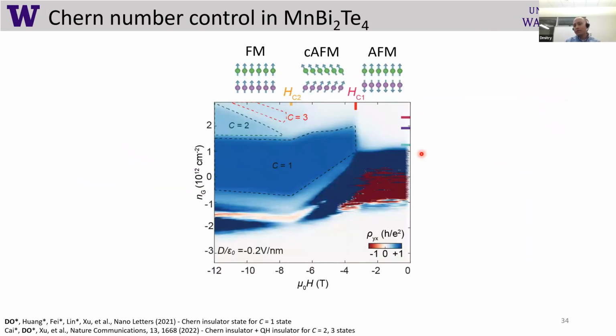So now when we have these higher quality samples, what we can do with them, we can do many things. And one thing we can do, we can map out at very low temperatures. So this is 50 millikelvin data. We can map out the Chern number as a function of gating, as a function of magnetic field, and also as a function of electric field. So we can, for example, fix electric field, sweep doping, and also sweep magnetic field and get this map.